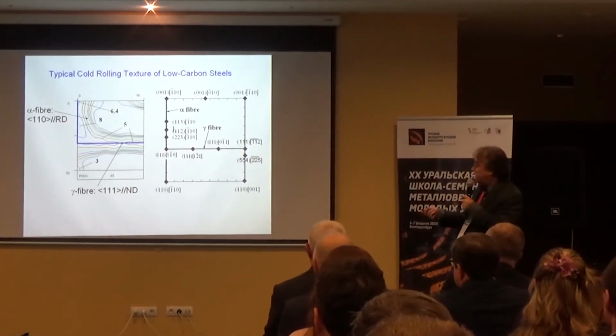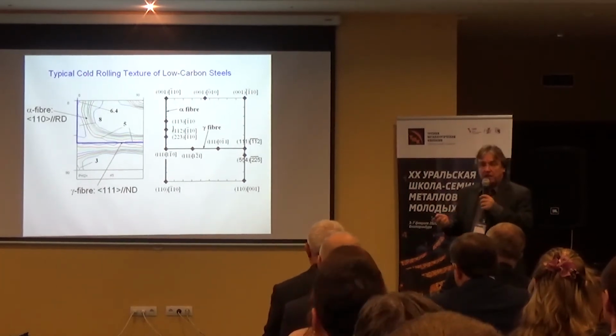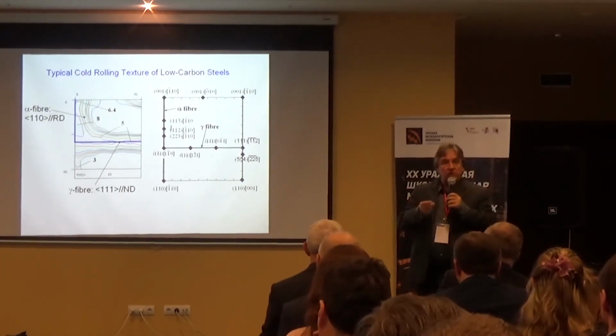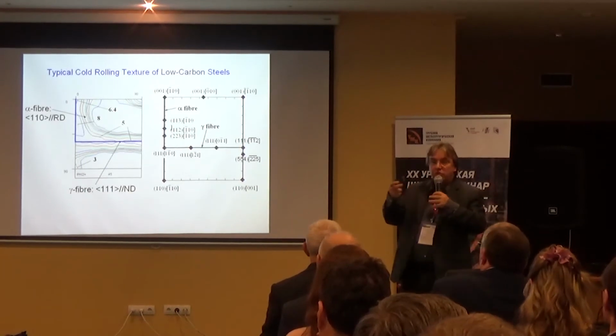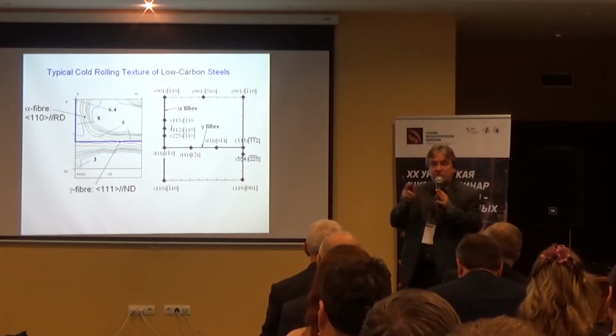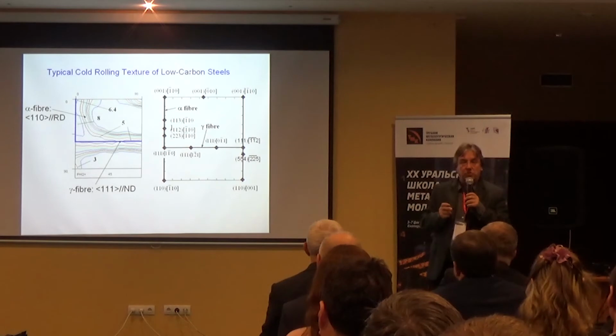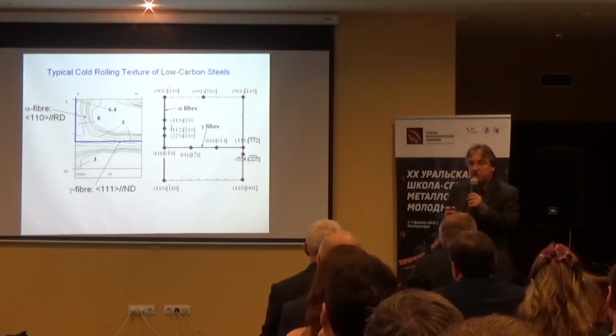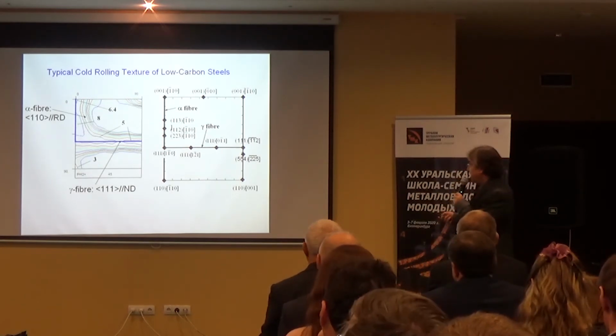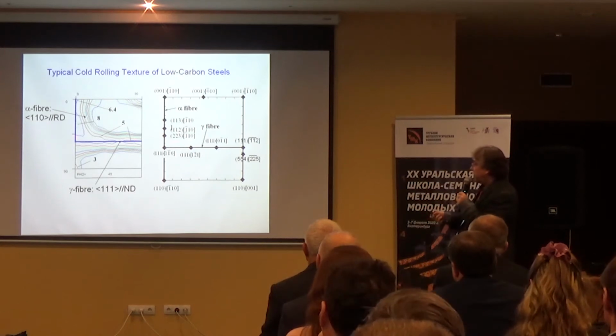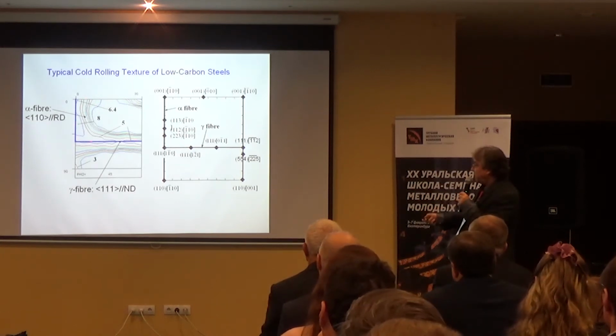This is only the case for cold rolling and annealing. So if you do wire drawing, for example, or extrusion or forging, then textures may be totally different, and you need to consider the real three-dimensional Euler space, but not in this case. So here, typically for the cold rolling texture is that we have two fibers.